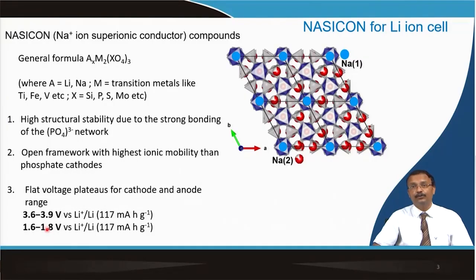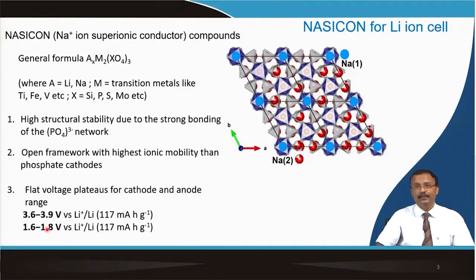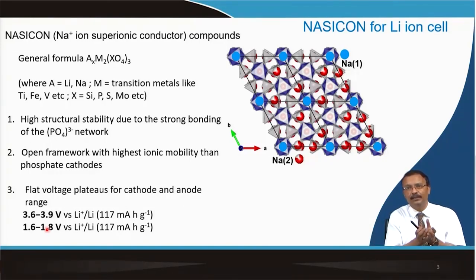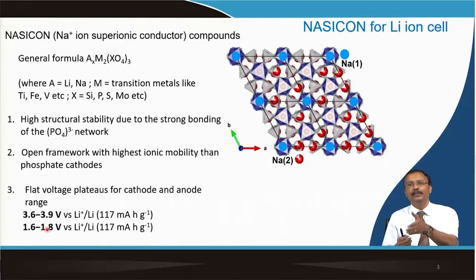This material has been studied for sodium-ion batteries — it is not a new material. But what we plan to show is that this particular material can now be used for lithium-ion intercalation. Since sodium is present, the idea is to first get rid of the sodium using a lithium-ion based electrolyte, put lithium inside the structure, and then cycle it. Sodium cannot readily enter the anode structure, but lithium from the electrolyte can pass and go to the anode site.